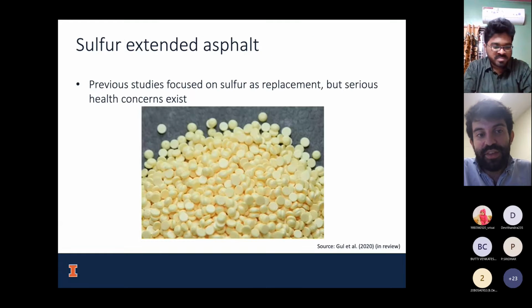The first one that I think is most critical is, and I'm unique in thinking this is most critical, most people kind of overlooked it, but I think sulfur is a very good option, because sulfur is so widely available and we know that the performance is good. So in this paper that we did, we looked at the sulfur as a replacement for asphalt binder in the mix, and also for the asphalt aggregate. So you can add it by what they call wet method or dry method, right? Where you blend the binder with sulfur first, or you just blend the whole mix with sulfur and it's more like an aggregate.